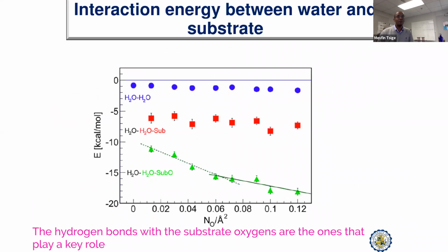The benefit of our simulation is that we can go further and explain why that happens. We calculated how these individual water molecules interact with the surface. So we determined the interaction energy as a function of degree of oxidation for three different kinds of water molecules. The free water molecules close to the surface have an interaction energy on the order of 1 kilocalorie per mole, which means the dynamics of those water molecules is controlled by thermal fluctuation. The substrate has nothing to do with controlling their dynamics and lifetime. That's why we didn't see any dependence on the substrate type.